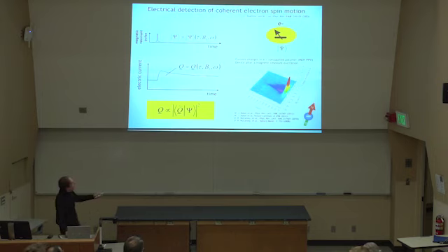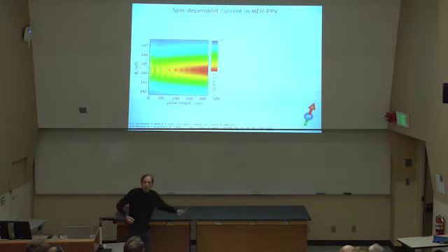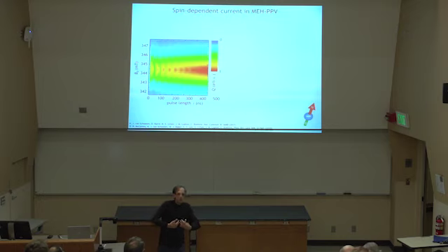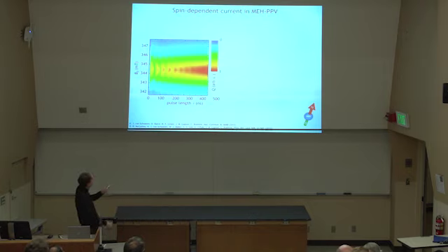And the answer is, you take this experiment and you repeat it many, many times with changing excitation parameters of your paramagnetic state. And that should give you, for instance, the length of that pulse, and that should give you essentially a projection of this coherent spin dynamics during your pulse application. So what you see here is now a plot of this charge that comes out of the integration of those transients that I showed you as a function of pulse length.